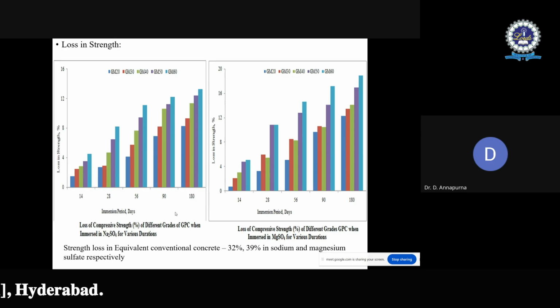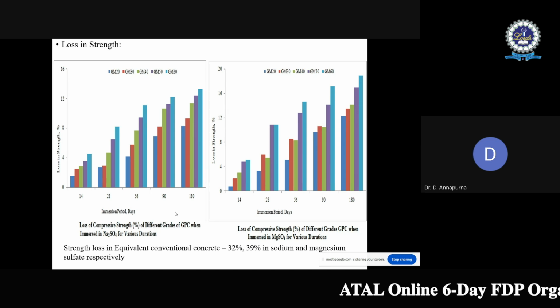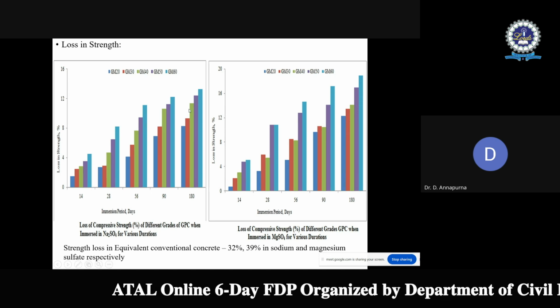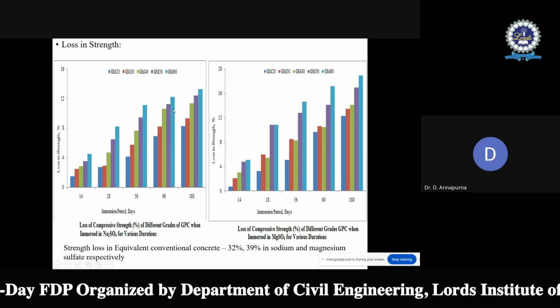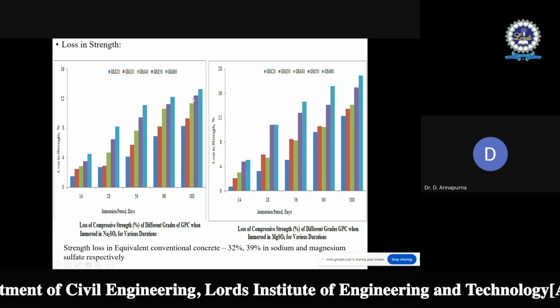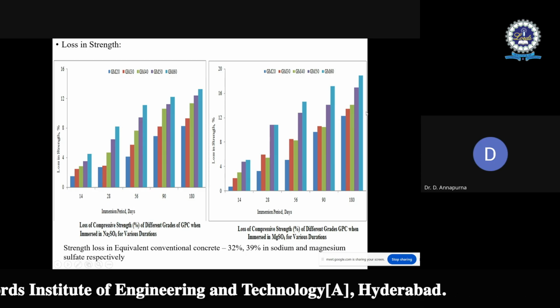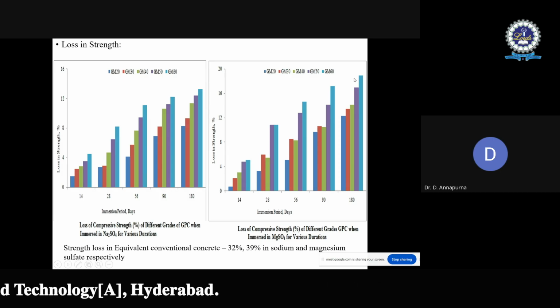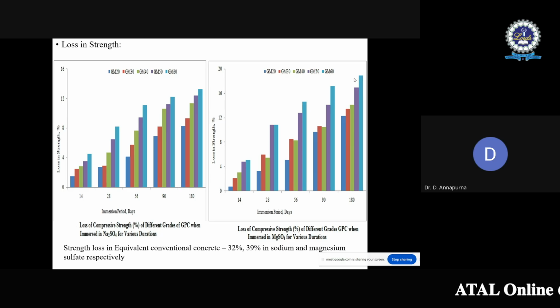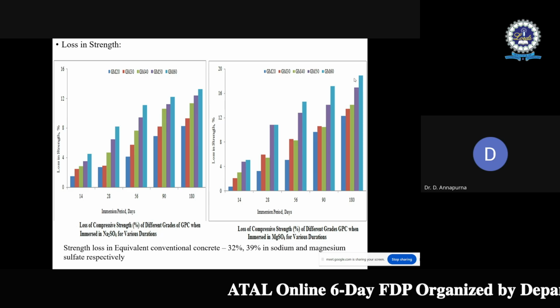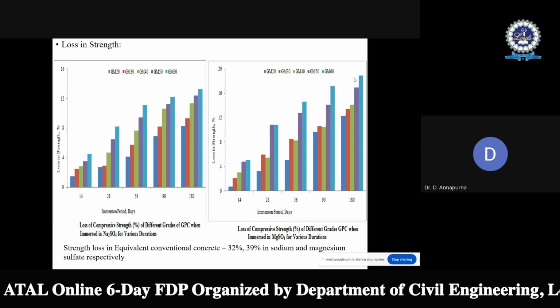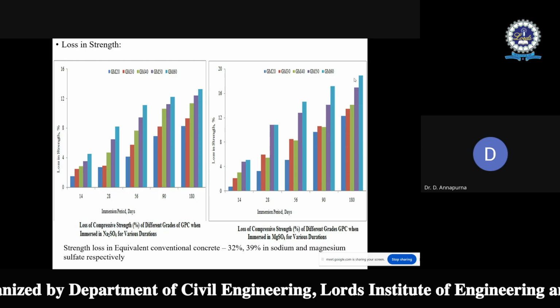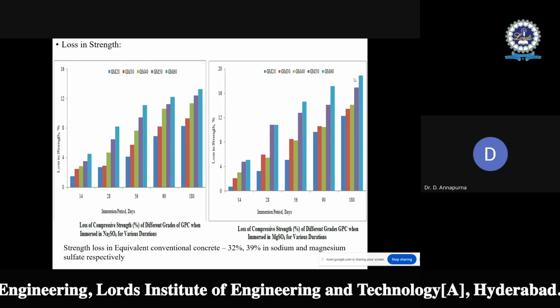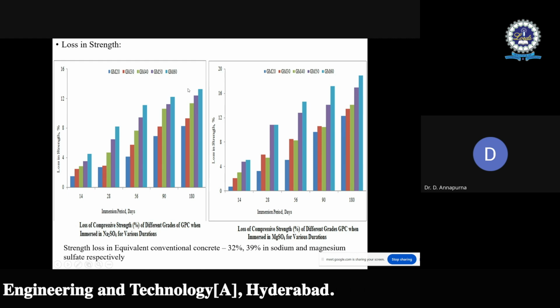In the loss in strength, it is observed that the loss in strength increases with increase in grade of concrete. Surprisingly, as the grade of concrete increases, the loss in strength increases when it is exposed to sodium sulfate and magnesium sulfate. The probable reason for this behavior may be attributed to the higher calcium content reacting with sulfates, because the GGBS dosage is increased, which has calcium content. So that calcium content is reacting with the sulfates, and degradation of material is occurring. Because of that, the loss in strength is increased.